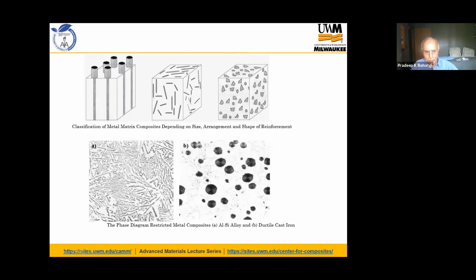Now, metal matrix composites made by casting have been used for a long time. This is a picture of a typical aluminum silicon alloy, which is in all cars, everybody's cars, the pistons and liners, silicon needles embedded in aluminum. And the second well-known metal composite is graphitic ductile iron, in which spherical graphite is dispersed in the matrix of iron. These two are phase diagram restricted composites, where the amount of silicon and its shape and the amount of graphite particles is restricted by phase diagrams and thermodynamics.